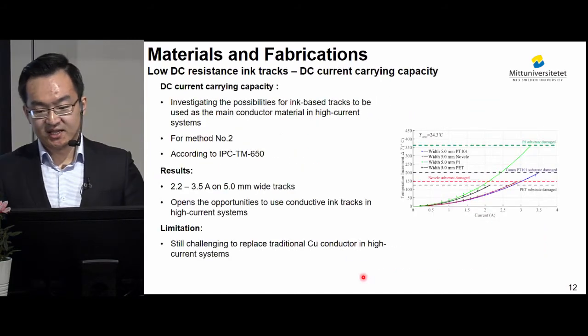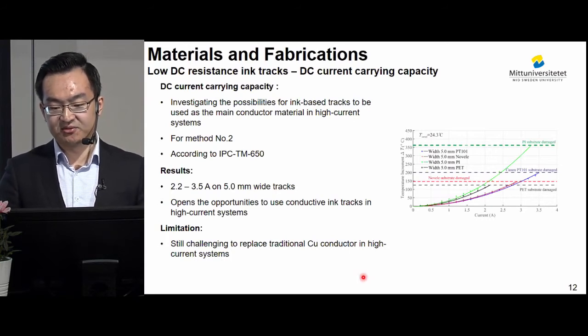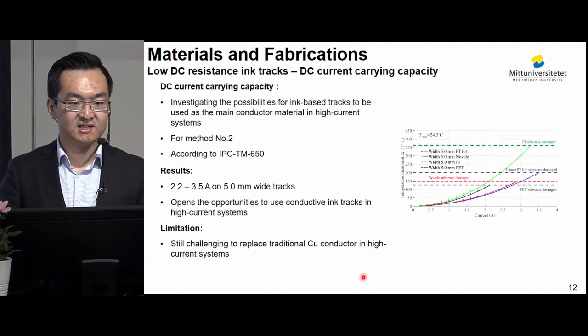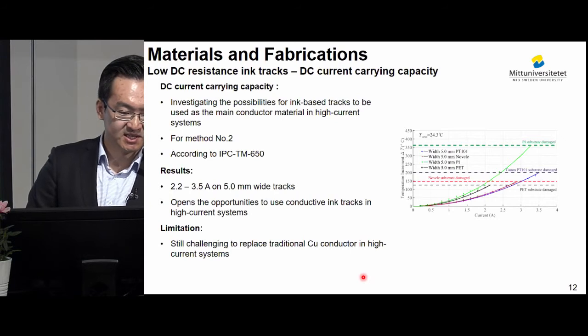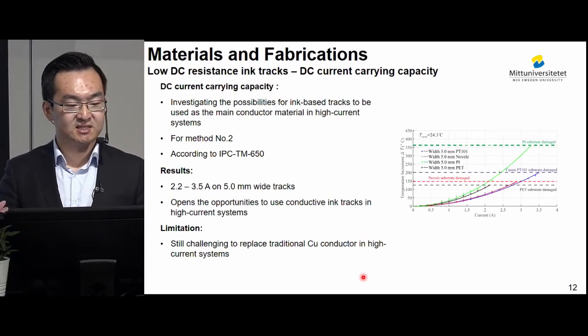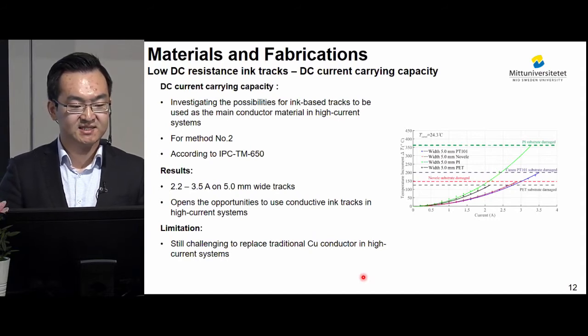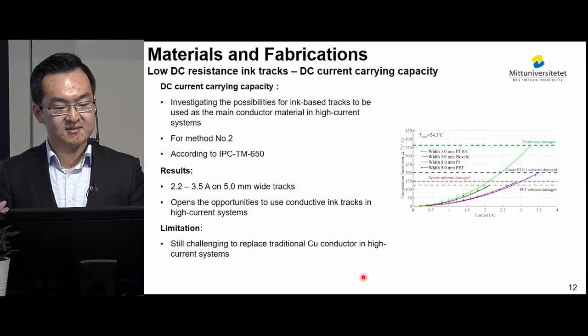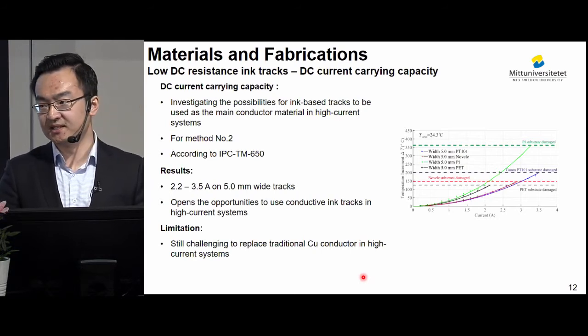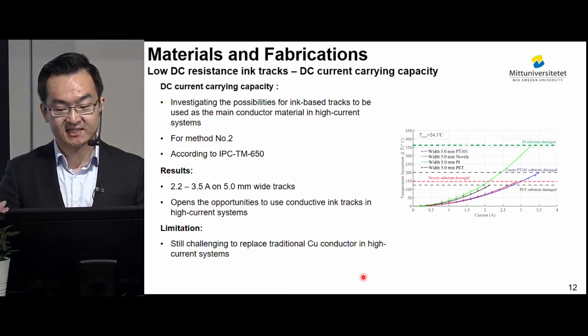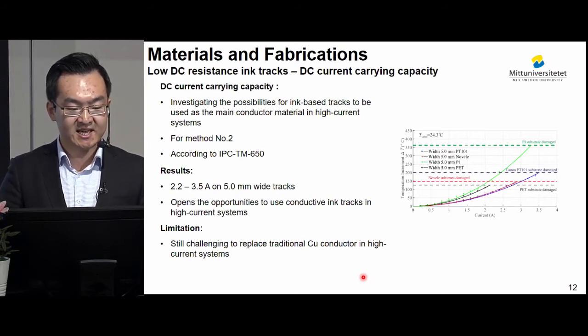And we also did current carrying capacity tests on the tracks made using method number 2. The reason why we do this is because we would like to investigate the possibilities for ink-based tracks to be used as the main conductor material in high current systems. And this test was conducted according to international standard IPC TM 650.